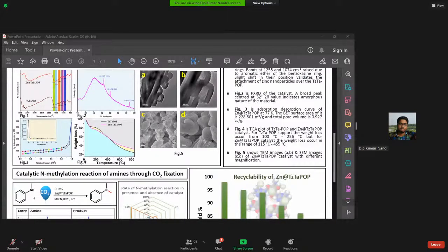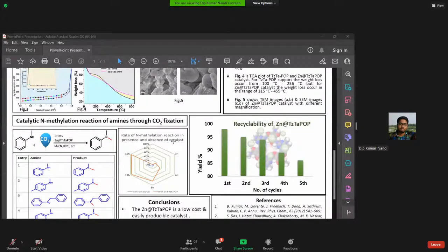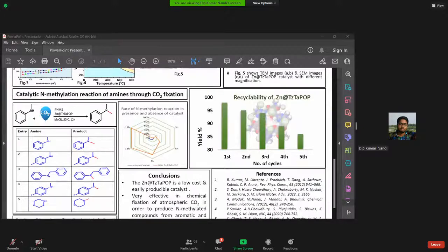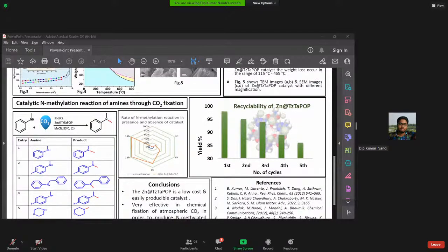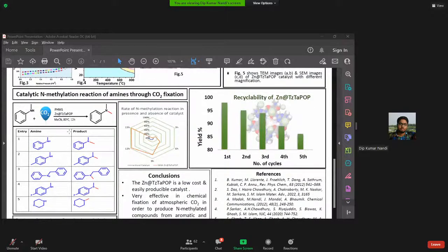Now, we want to utilize the CO2 from the atmosphere, so we did the N-methylation reaction. The scheme is shown here. As you can see, the hydrogen from this amine group is replaced, and a methyl group is added here. The N-methylation reaction was done using the Zn@TzTaPOP. The reaction condition here is 80 degrees Celsius, which is not so high, and the reaction is complete within 12 hours.